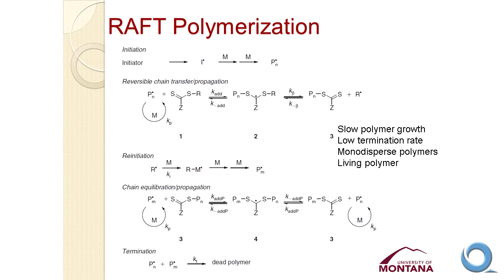So what we use is RAFT control of the polymerization, and the trick to this process is this chain transfer agent. The chain transfer agent has the ability to stabilize a free radical. It has a stabilizing group, Z, which in our case is a substituted sulfur group, and it has a leaving group, R, which can leave the chain transfer agent as a free radical. So we initiate the polymerization the same way, but we use a very low concentration of initiator.